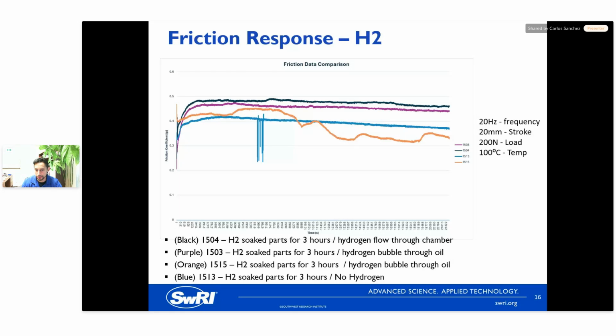And then the lowest one would be that blue curve there, hydrogen soaked for 3 hours and then no hydrogen, where we basically turned off the system. It's still a higher friction coefficient, but you can see how it drops off. But in a lot of cases, depending on how the hydrogen actually interacts with your surface, you'll get kind of an erratic behavior, which you see pretty frequently in these friction coefficient curves. And we ran numerous repeats of the same type of conditions, and saw that running with hydrogen, it's not as repeatable as running it in the standard, open environment type setup. But in all cases, you'll typically see an increase in friction coefficient, whether it's a smooth curve or a kind of erratic curve like you see in that orange one there.